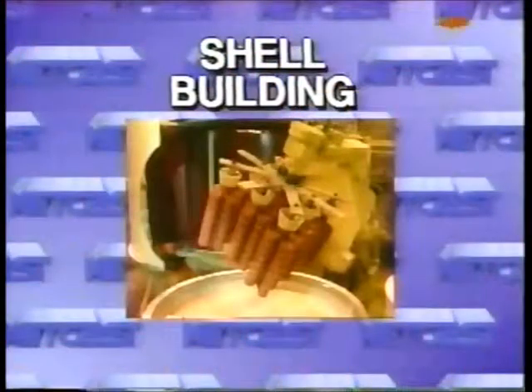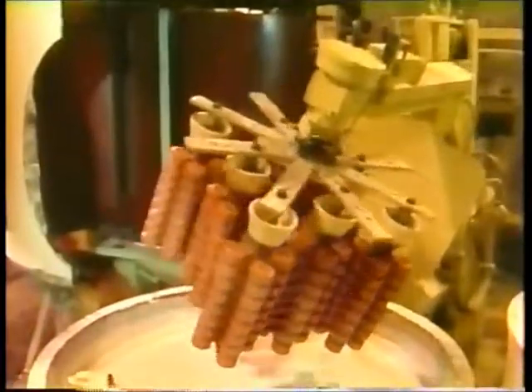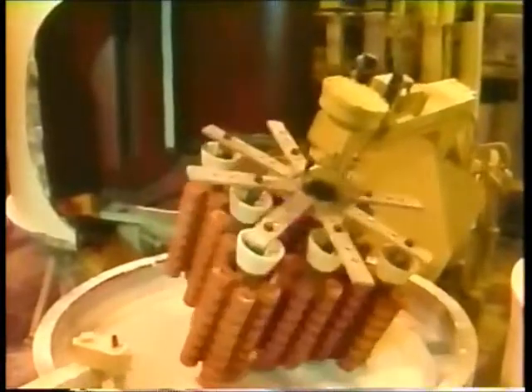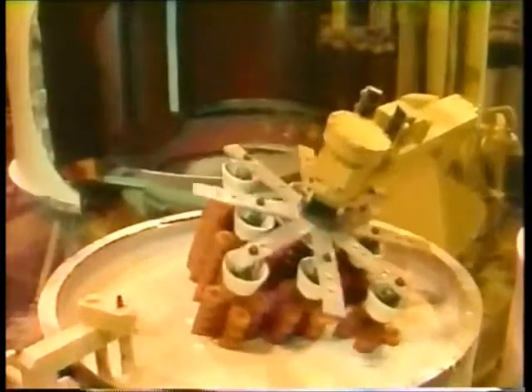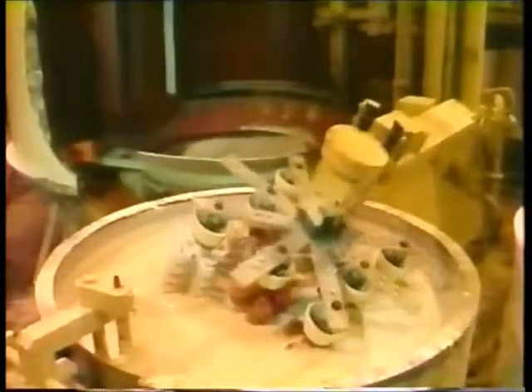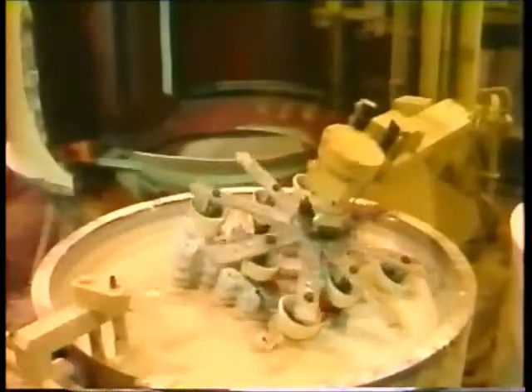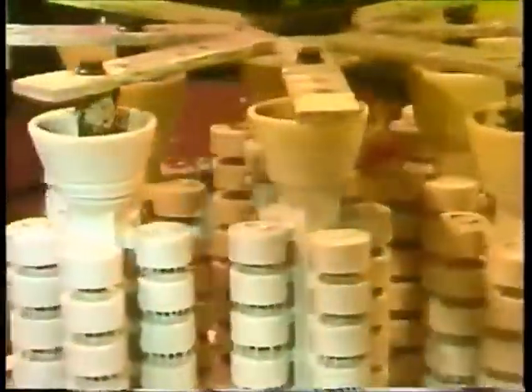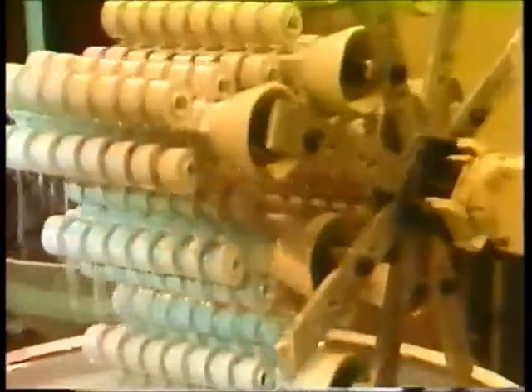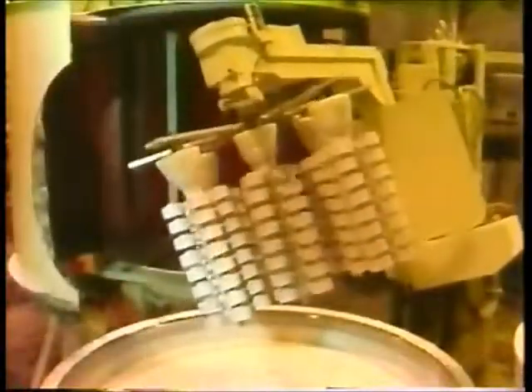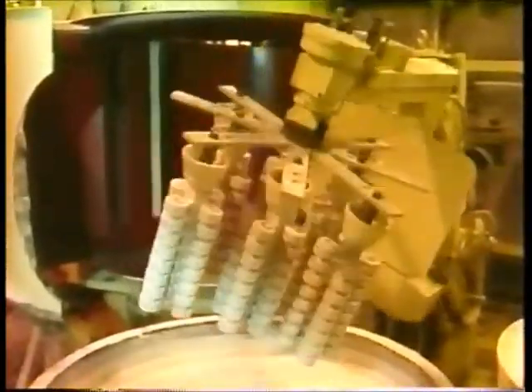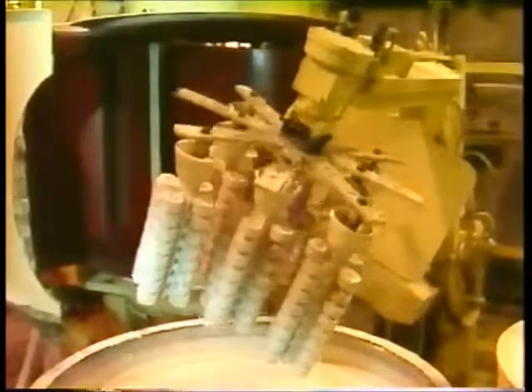The completed assembly is then processed to produce a ceramic shell mold. This is accomplished in several stages. First, the wax assembly is dipped into a cleaning or etch bath and then pre-wet before it is dipped into the first coating of slurry. This is a critical step in the process, for the operator must produce an almost flawless coating upon which to build the shell. The assembly is carefully examined, and any bubbles in the coating are burst with an airstream.